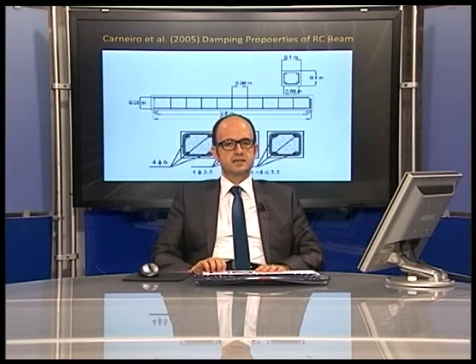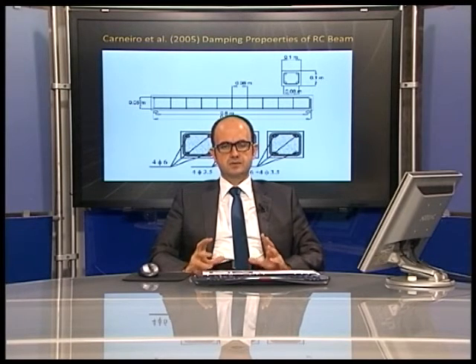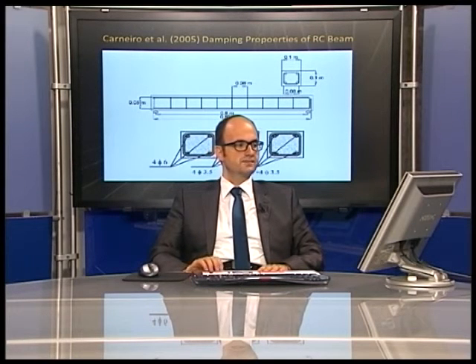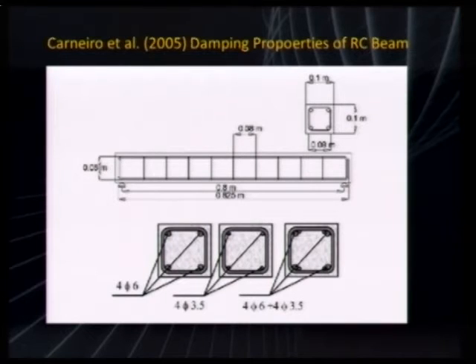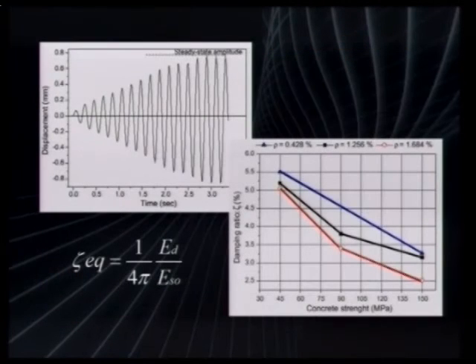Let's look at the past studies to verify our experimental findings and to understand the experimental or analytical findings of previous studies. Carneiro performed one study. This is actually a very simple beam, and there are different reinforcement configurations here. The reinforcement increases by number and by diameter, and they performed cyclic tests on this reinforced concrete beam. They determined the displacement in time, a sinusoidal type displacement.